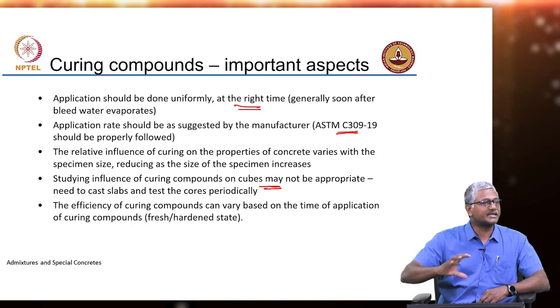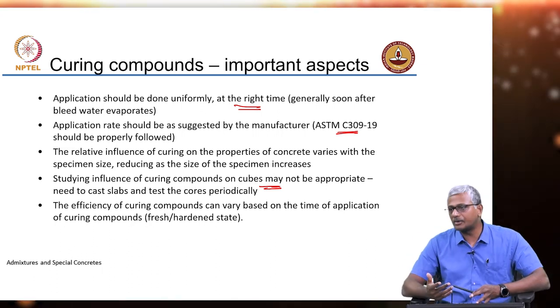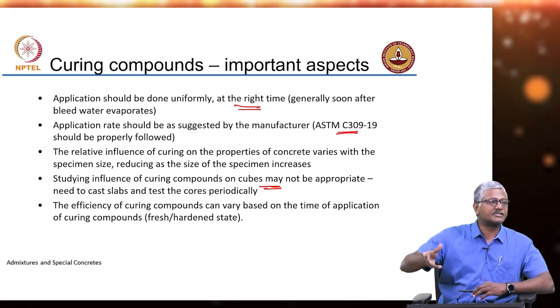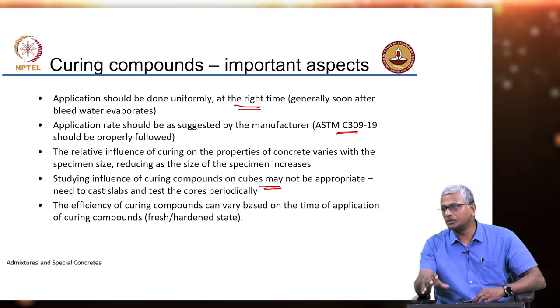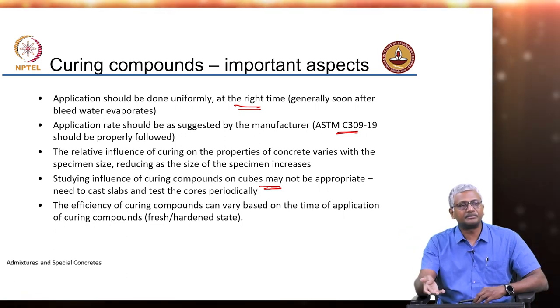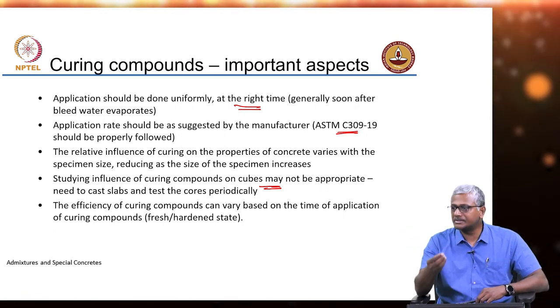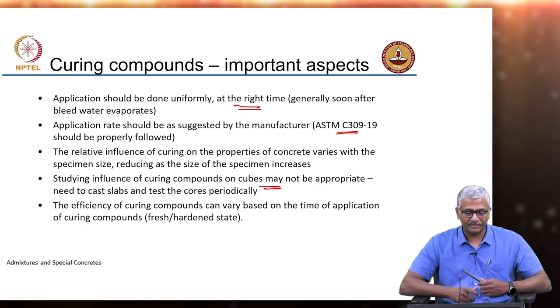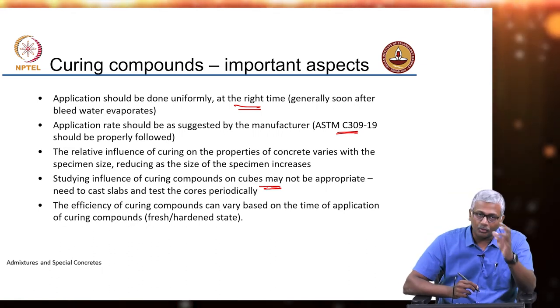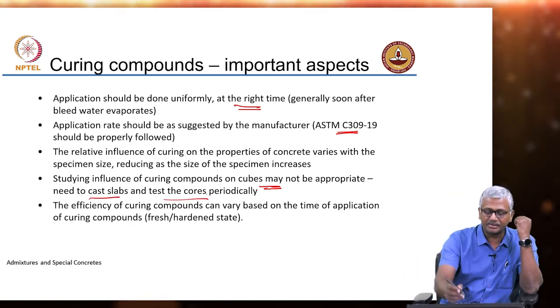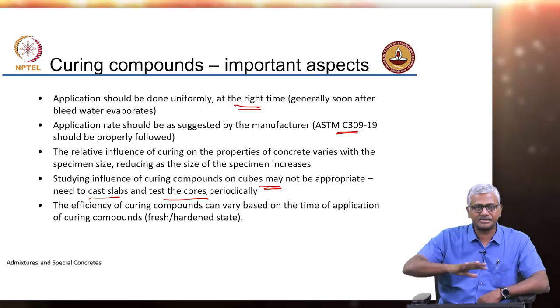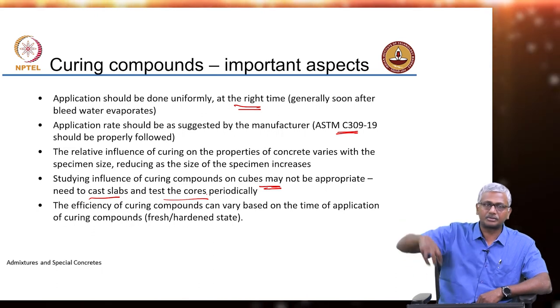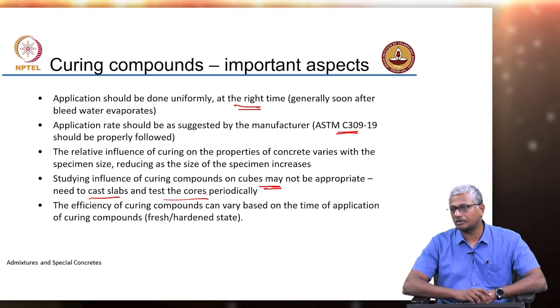In a cube, all 6 surfaces are likely to experience drying. So the amount of surface available for drying as a function of the volume in a cube is quite different compared to what you have in a slab or a beam. It is probably more justifiable to cast slabs, apply curing compounds on the top surface, and then use cores from time to time to assess the strength of the concrete. That may be a better approach.